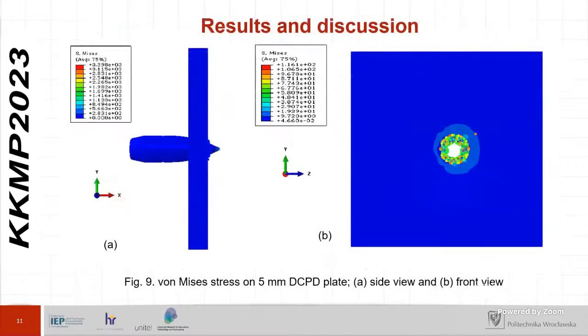Now for the resulting discussion, we can see a complete penetration. That is, this 5 millimeter thick plate is unable to stop this bullet. There was a complete penetration in which you can see that the material fractured here. You can see the particles. We set this up before so we can have this information. We have the fracture strain, so we use the condition of the fracture strain so that whenever it gets to that point, we have this kind of information. And this is what it looks like in real life when you shoot it. So there's a full penetration with these bullets, considering this thickness. This is the side view, and this is the front view, and we have the von Mises stress information here from this slide.